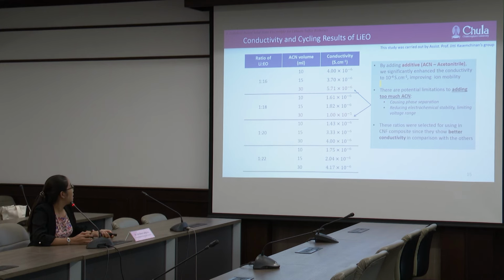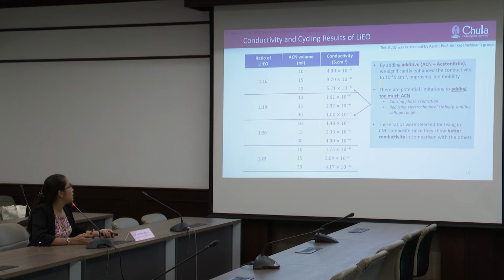And we find that by adding an additive, namely acetonitrile, we significantly enhance the ionic conductivity. However, there is a limitation to adding acetonitrile. The maximum amount of acetonitrile is about 30 milliliters. If we add too much acetonitrile, it can cause phase separation and reduce the electrochemical stability.